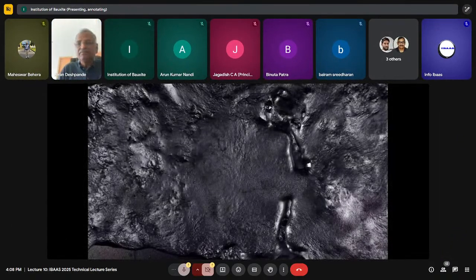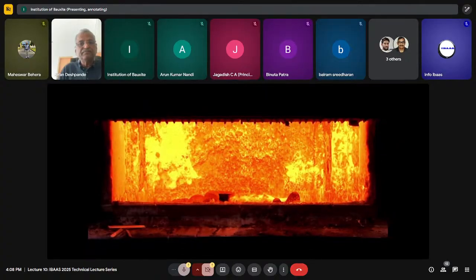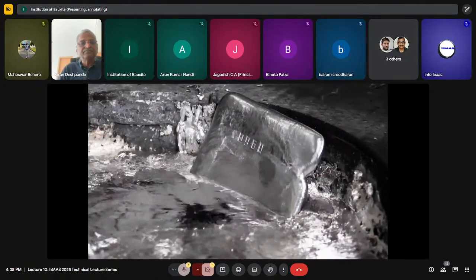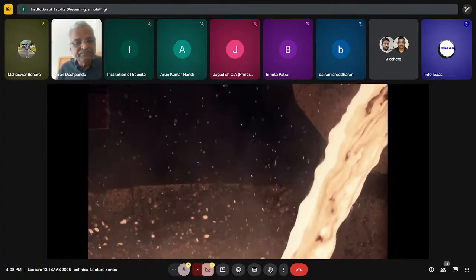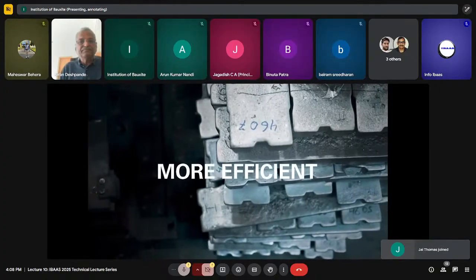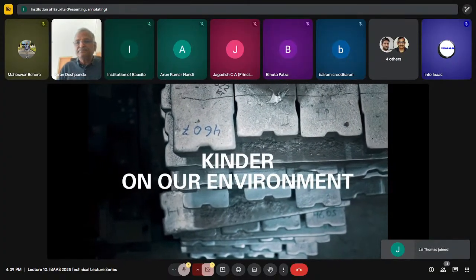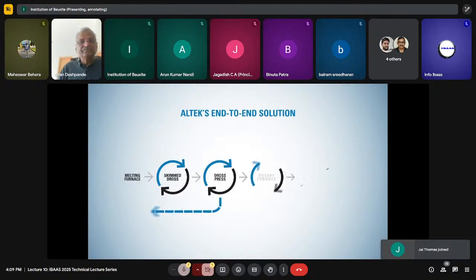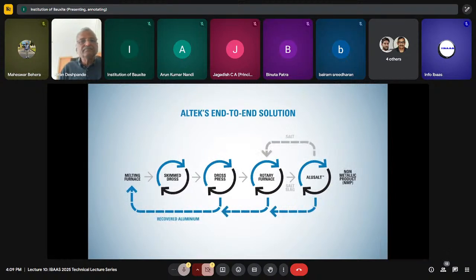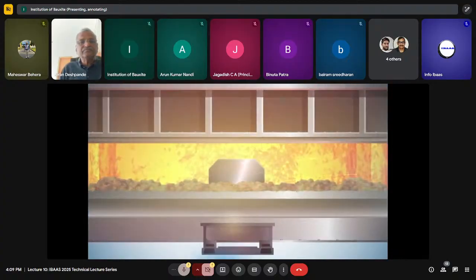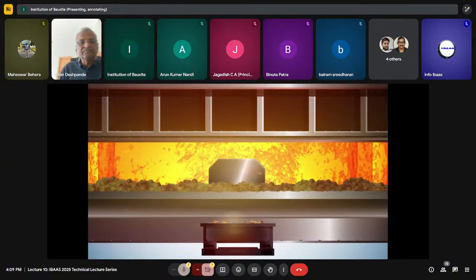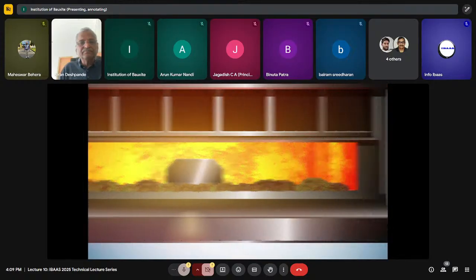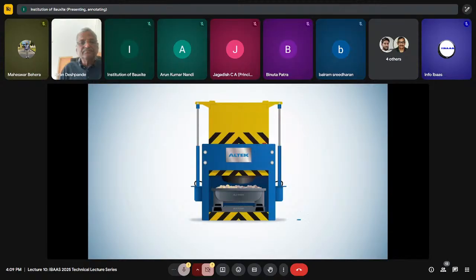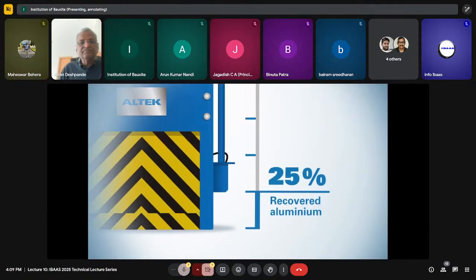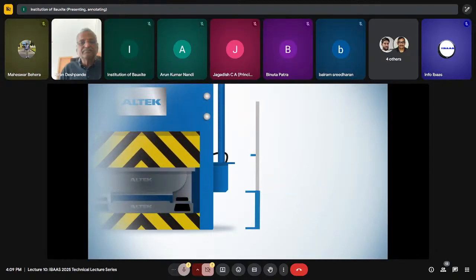Since the very early days of aluminium production, very little has changed. Today, ALTEK is rethinking, modernizing, and transforming the entire cast house, using the latest technology to make it more efficient, more productive, and kinder on our environment. Just think of what that could mean for you. We start with a furnace, where the dross is skimmed into dross pans. This is then transferred immediately to the ALTEK dross press, where large amounts of aluminium are recovered, often as much as 25% being squeezed out of the dross, and recycled back into the furnace.